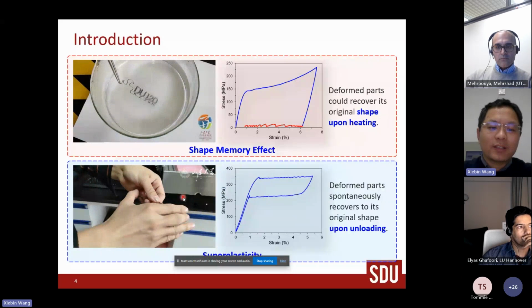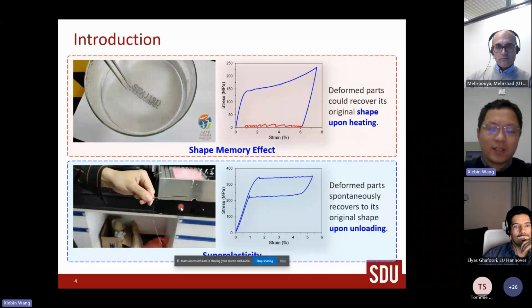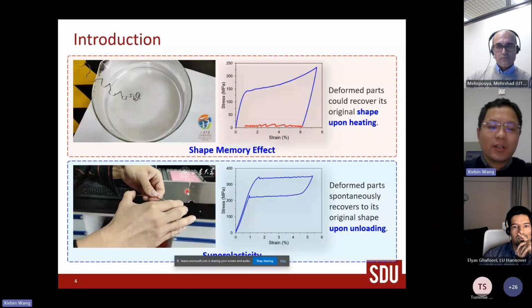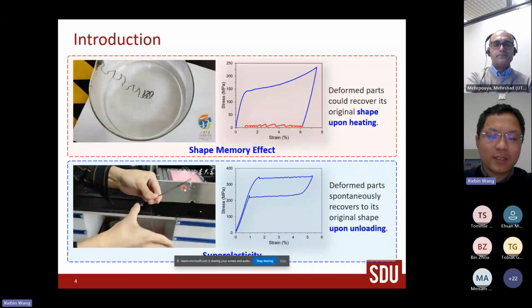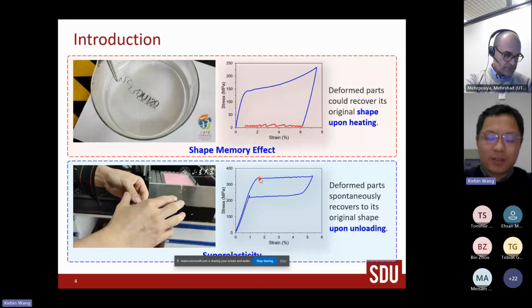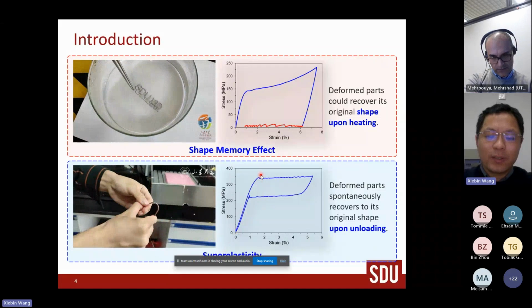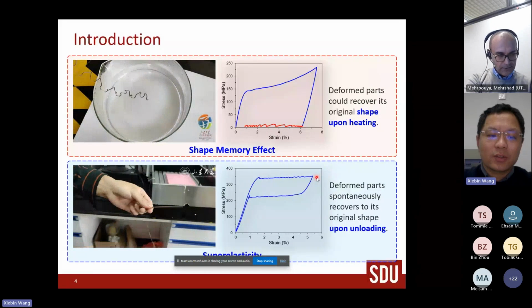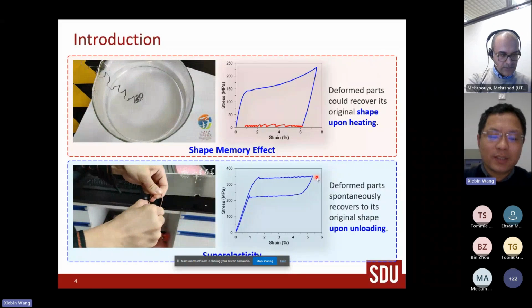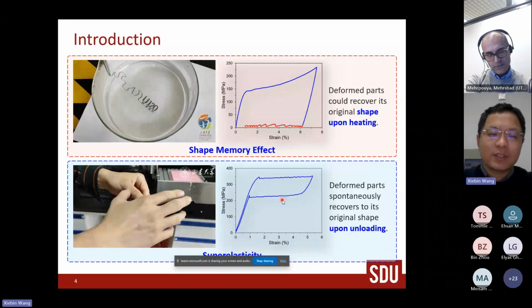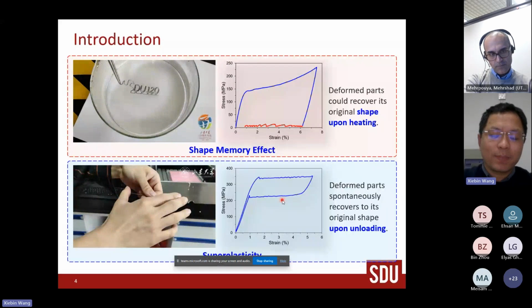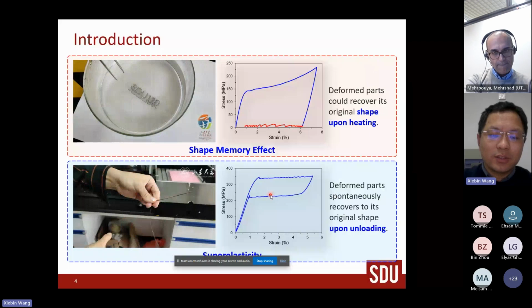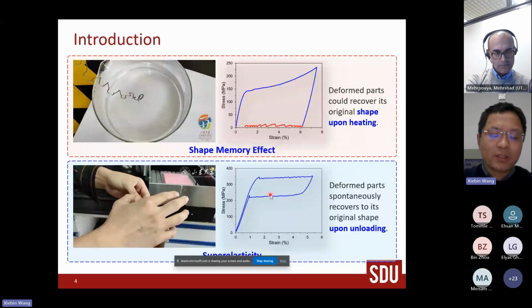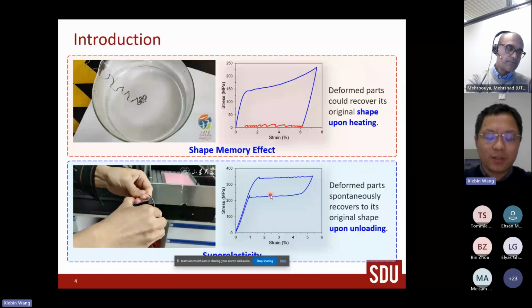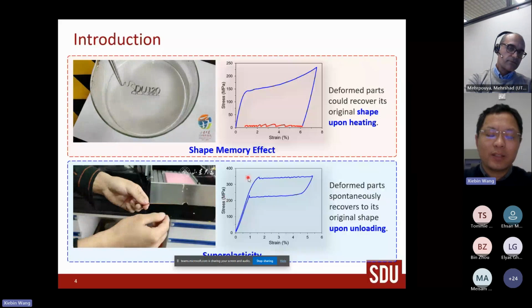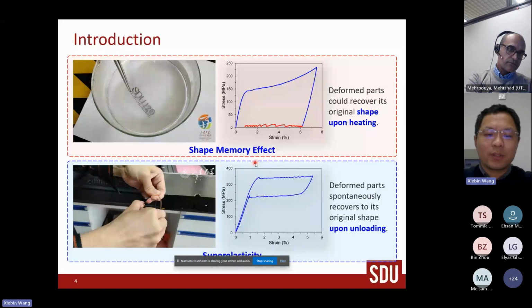And it also shows superelasticity. If you look at the video, it looks like this kind of alloy has very good elasticity. Look at the curve, if you deform it, it shows a plateau. This is caused by stress-induced martensitic transformation, and during unloading, the martensite transforms back to austenite phase. In the meantime, the shape of the material also recovers back to its original shape. So this is called superelasticity, mainly caused by the transformation between austenite phase and martensite phase.